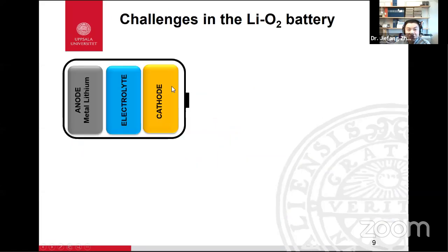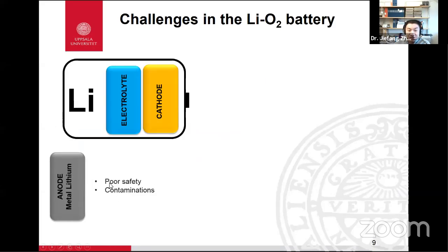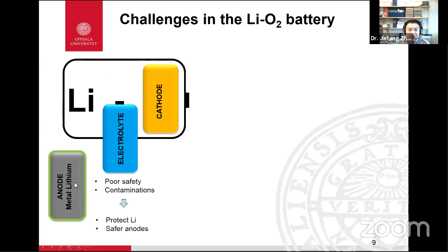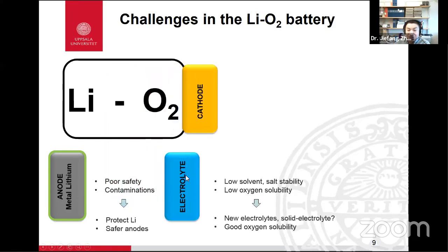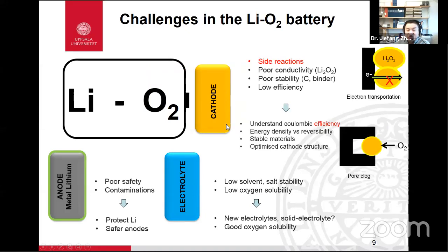Okay, so there are lots of challenges in this technique, the lithium oxygen battery, for commercialization. There is a problem with safety in the lithium part, because lithium is very active, and also in the electrolyte part for the decomposition, and the cathode part also. So the problem is that all the components involved in the lithium oxygen battery are very active, like lithium, oxygen, and so on. And also there are some technical issues, like the low efficiency of the lithium oxygen battery. Now we focus on these two parts: one is side reactions, another is the efficiency.